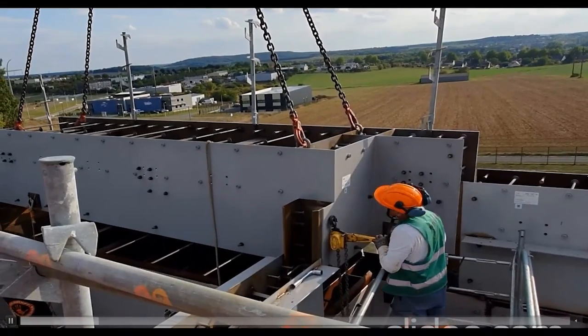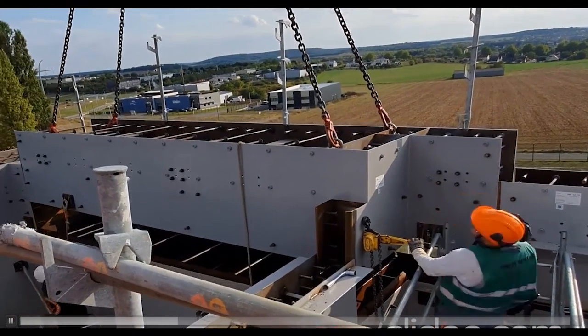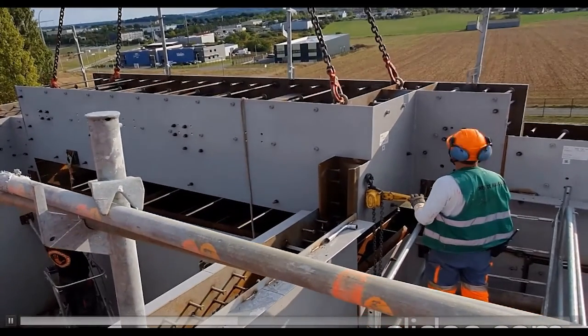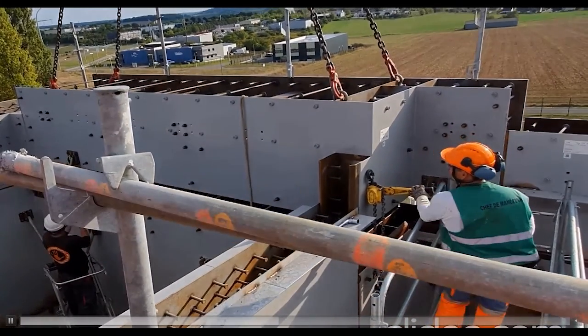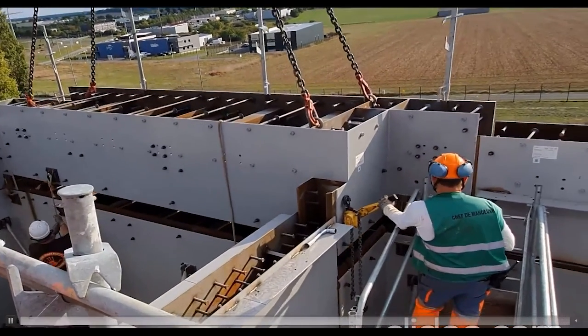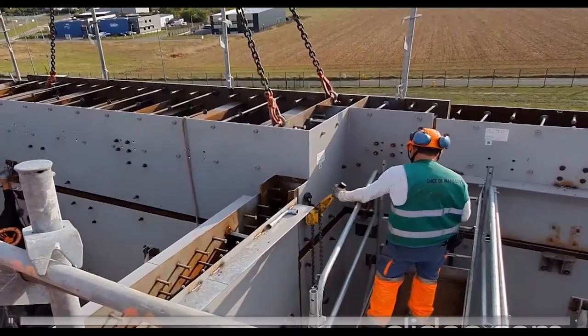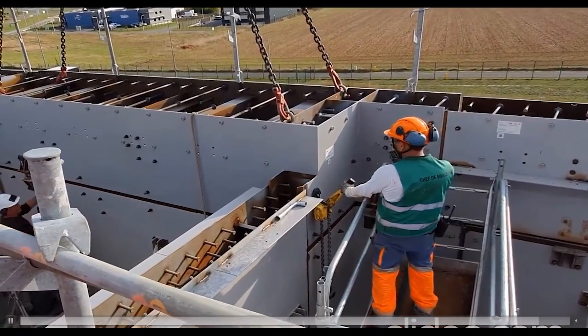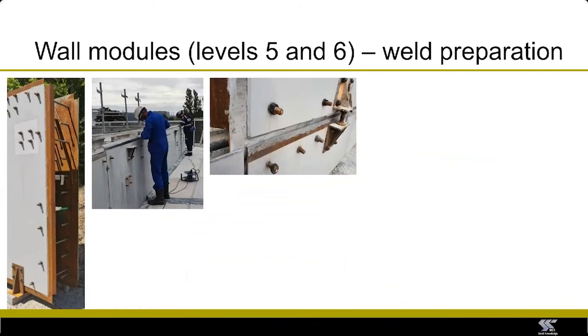And this clip shows the installation of a module that is to be fillet welded. And you can see the guide plates here fitting into the adjacent module. There was some preparation for welding to be done, partly because the modules were on site for a period of time without the edges to be welded being protected. So rust developed on those edges, and that had to be removed before the welding could proceed.